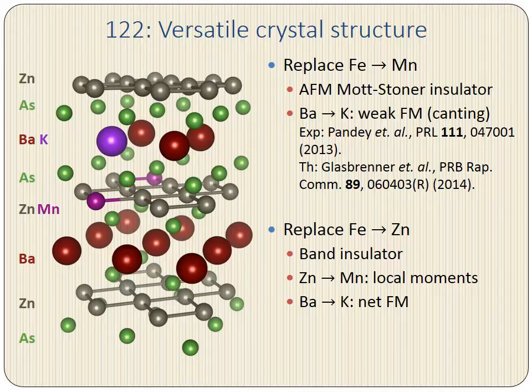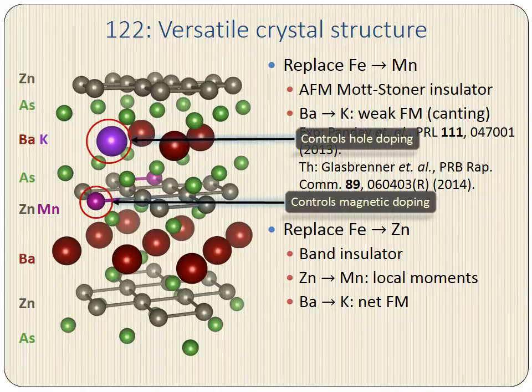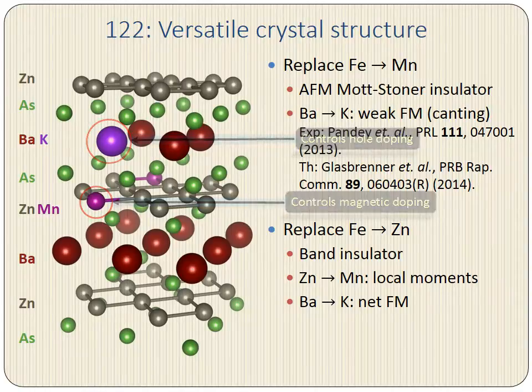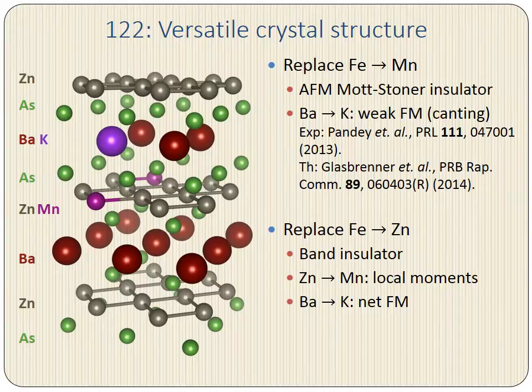Unlike the standard DMS materials, here we have an independent control of hole doping and magnetic doping, which is useful for material synthesis, and also this independence means that there is a shot at developing a theory of the magnetic interactions in these systems. In both barium manganese arsenic and manganese-doped barium zinc arsenic, we saw the onset of ferromagnetic order upon hole doping.